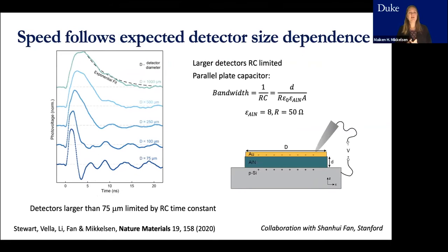We wanted to understand the speed in a little more detail. So to do that, we modified the detector size because, as I mentioned, there's a dependence on the area here. So we can consider these structures as basically a parallel plate capacitor where the bandwidth is 1 over RC. So you could see it is inversely proportional to the area. So as we get to larger areas, the bandwidth or the speed is going down. And that's also what we see in the experiment on the left here. This is a 75 micron detector diameter, and it goes up to 100, 250, and so on. And you can see the speed is slowing down significantly.